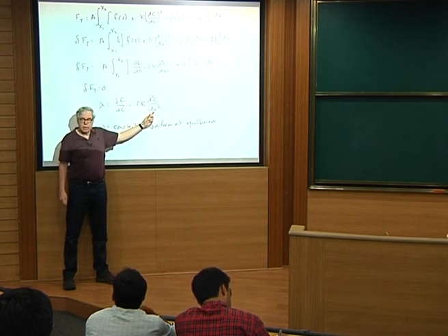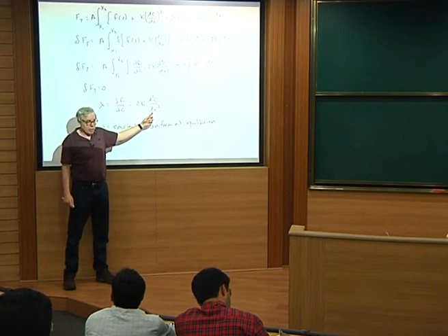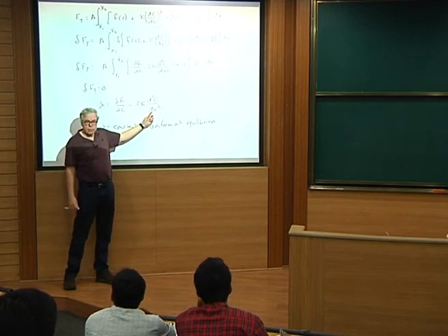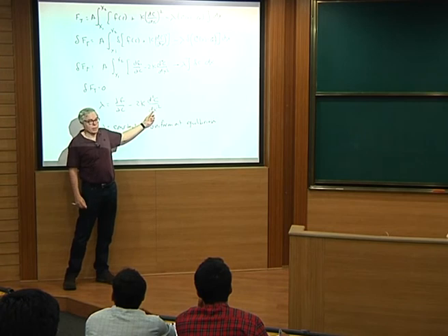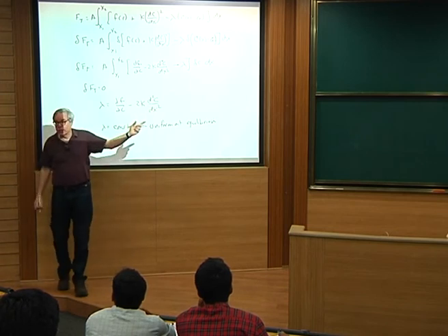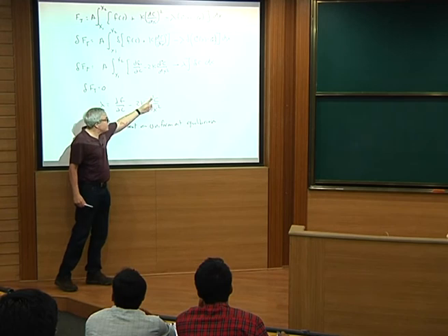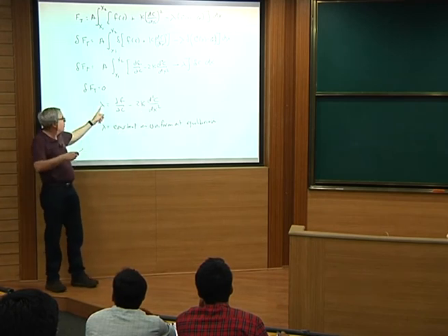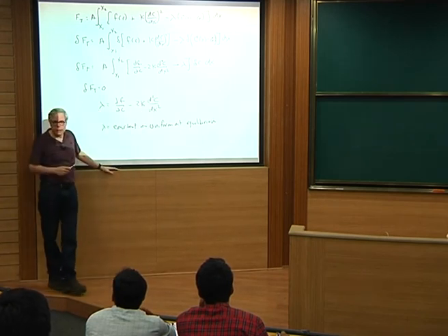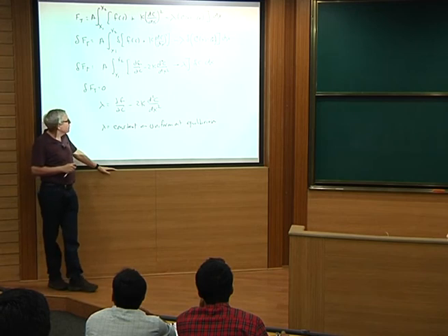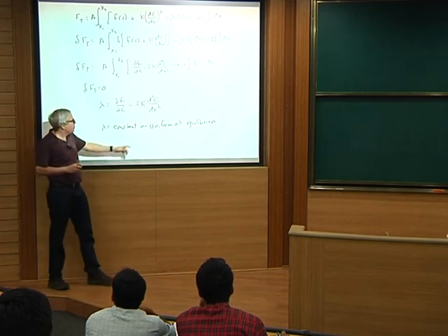Feynman had this famous line that if a good physicist can determine the answer without doing any mathematics, and here's the mathematics. So John Cahn knew this was going to be the answer before he did the calculation. So the Euler-Lagrange equation gives you the curvature and says that the chemical potential is a function of the curvature in the composition profile. Okay.